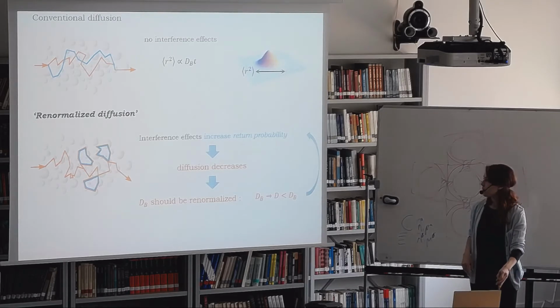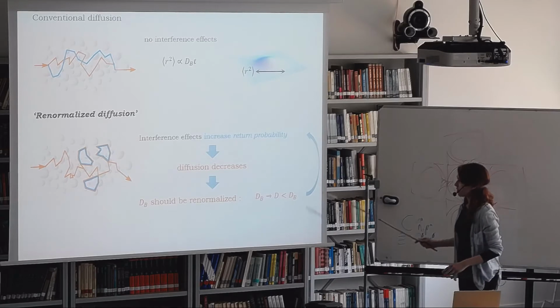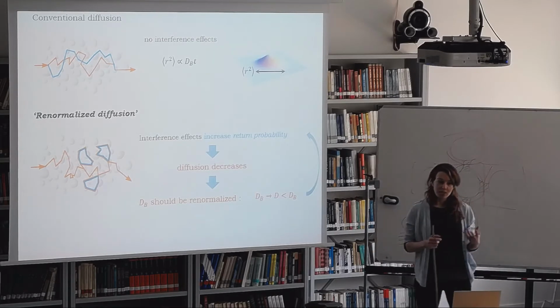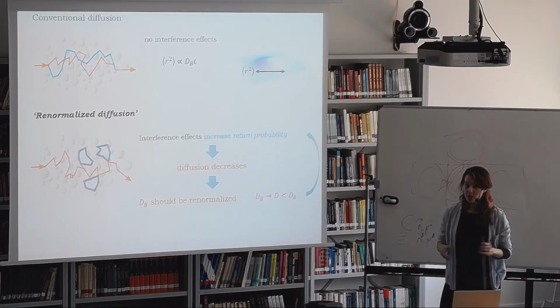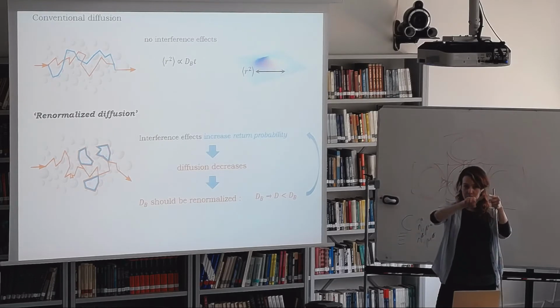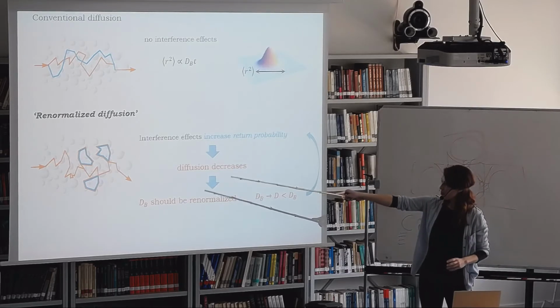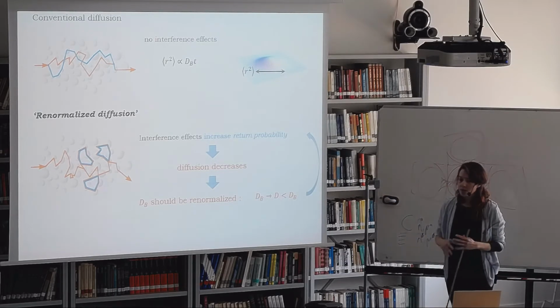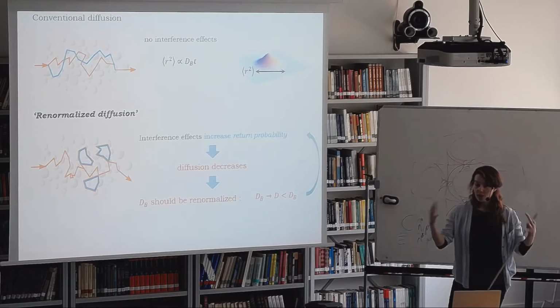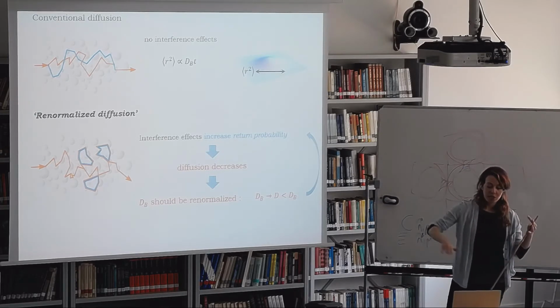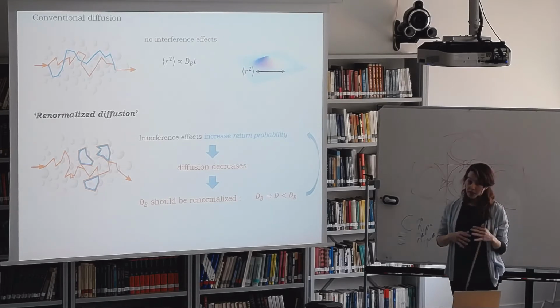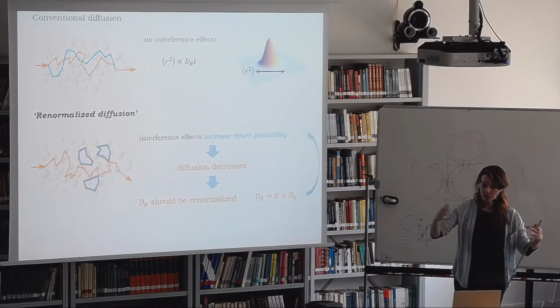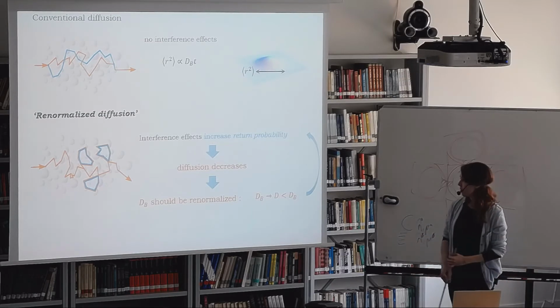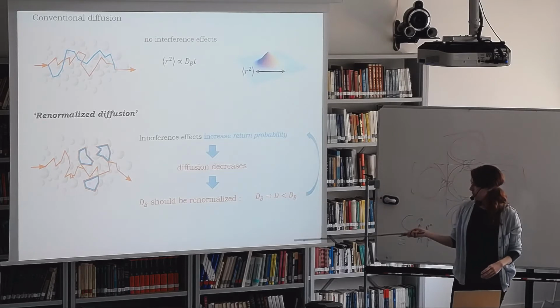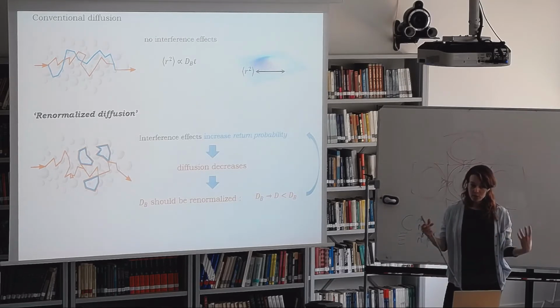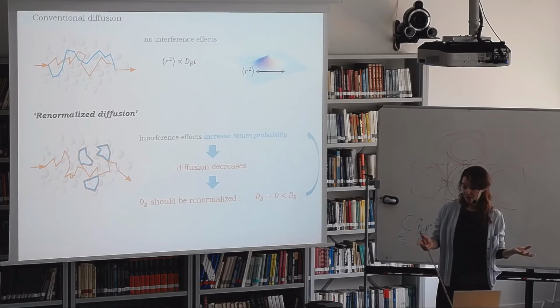So to do this, the basic idea is the following. We have these interference effects, and they are associated with an increase in the so-called return probability. So this is just the probability of your random walker to return to somewhere that he's previously been. This is sketched here with these little loops inside the sample. So if you have an increased return probability, then you're going to spend longer inside the sample because you're going to keep coming back to somewhere you've previously been. And so this is going to decrease diffusion because it'll take longer to spread out and longer to get outside of the sample. So this means that your diffusion coefficient should be renormalized. It should be smaller, right? Because diffusion is now slower.